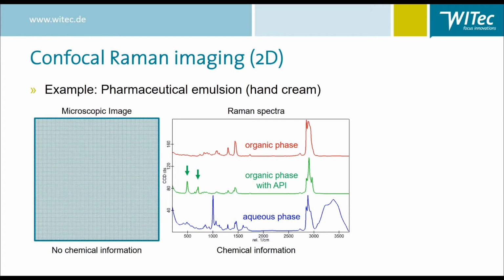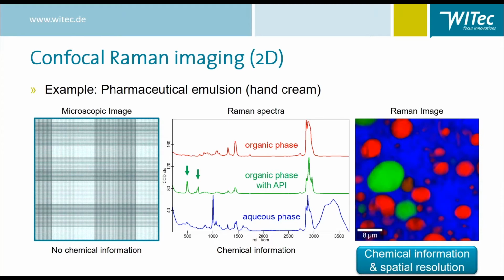This is done by defining the size of the measurement and the pixel size indicated here by this grid. The idea is to measure a full Raman spectrum at each individual pixel. Let's start the measurement. From the information in each pixel's Raman spectrum, it is straightforward to create a Raman image that shows the distribution of the different components. Image pixels in red color indicate positions where we have the organic phase without urea. Green pixels show the organic phase containing urea. And the blue pixels show the distribution of the aqueous phase, which forms the matrix in this emulsion. Pixel by pixel and line by line, we obtain the full Raman image, which now gives us the chemical information with a high spatial resolution.